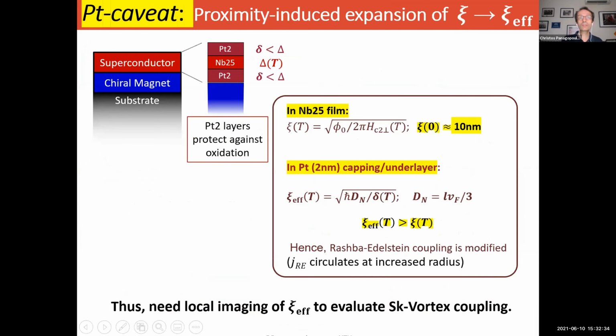Now, as I mentioned, there is what I call a platinum caveat, and that is because there is a proximity-induced expansion of the coherence length. These platinum layers protect against oxidation, but at the same time, because you have this 2 nanometers platinum on top of your superconductor, you have an effective coherence length which is larger than the pure superconducting coherence length of your system. And in order to measure this, you need a local imaging method of the effective coherence length so that you can evaluate the skyrmion vortex coupling.